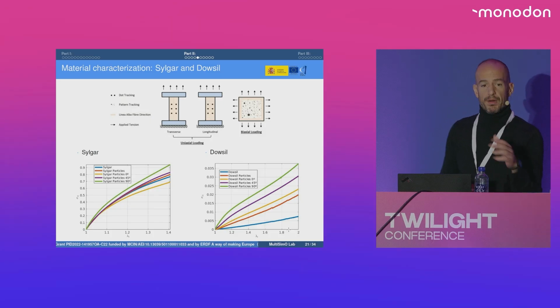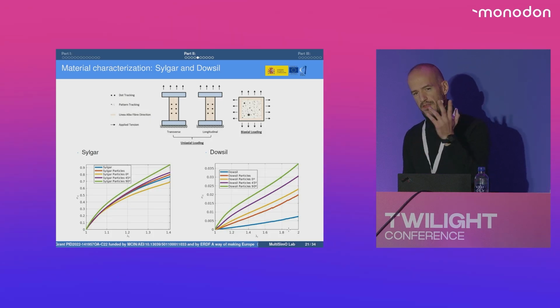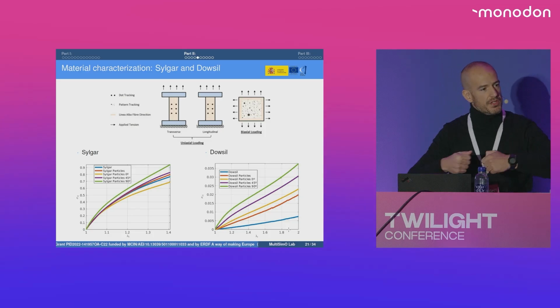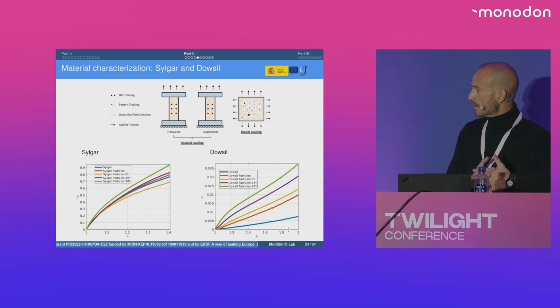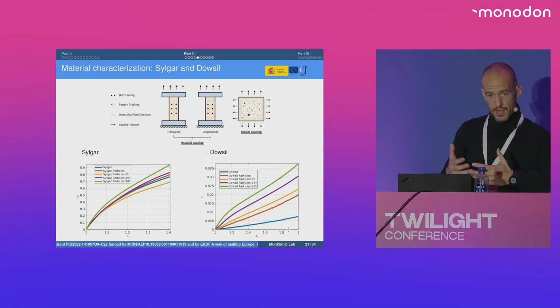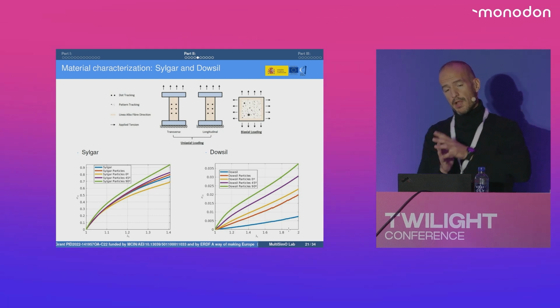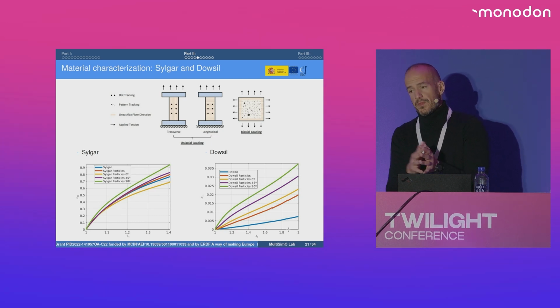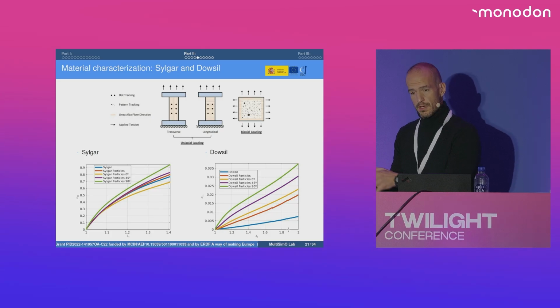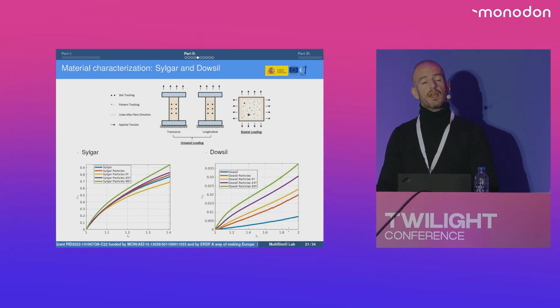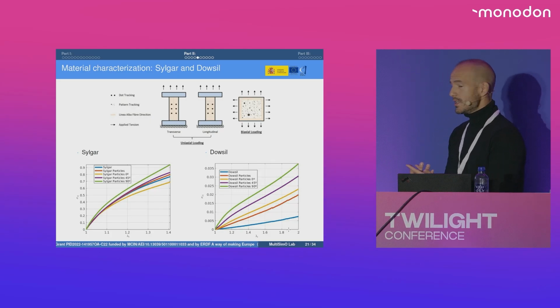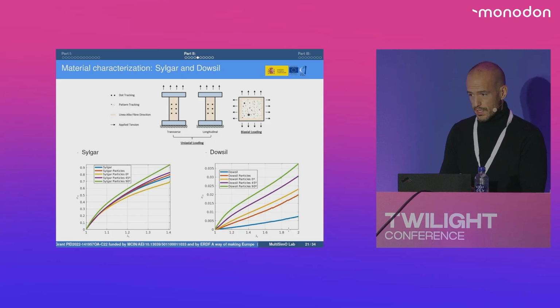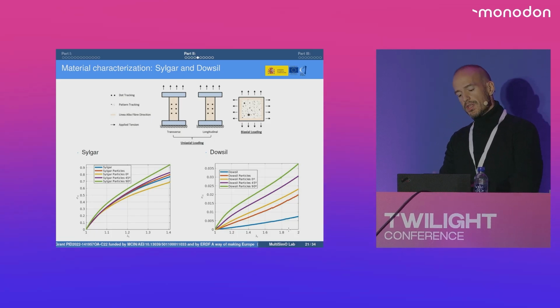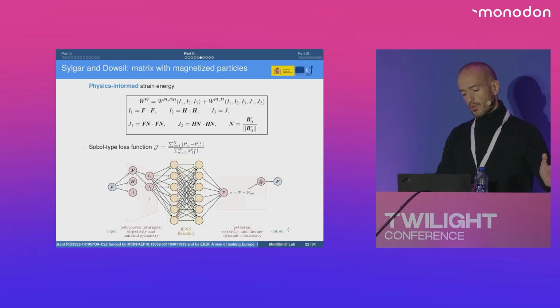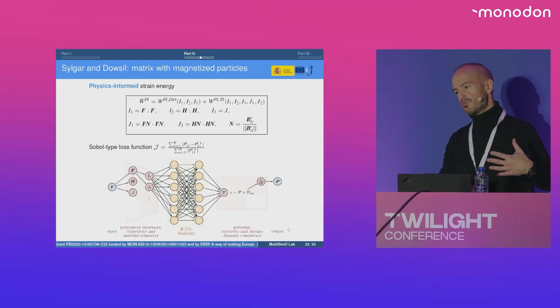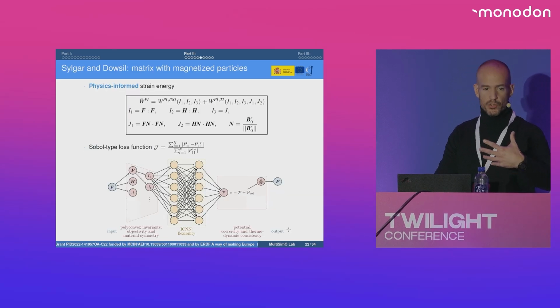And they embedded particles within this material with different concentrations. They carried out a uniaxial tension test, and they did it for the material prior to magnetization and magnetized in different directions. Okay, there is no magnetic field in these experiments; they are already magnetized, and the fact that the curves don't lie on top of each other is actually telling you that the material is anisotropic; it's not isotropic. Okay. So they carried out these experiments, and these experiments were good for us in order to derive a strain energy density, which is what I need in order to conduct simulations.